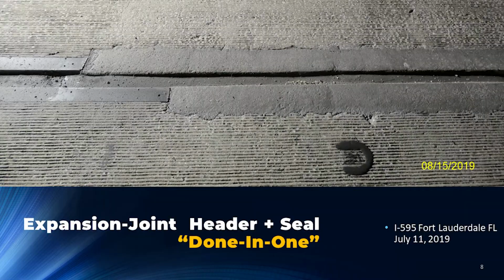So you can see it's pretty corroded, and we were able to reverse that on contact of the rebar without sandblasting. The other part of Phoscrete's ITD program is called the done-in-one, which means you can pour the header with MPC, then as soon as 30 minutes after the final pour, you can remove the foam board, prep and place the joint seal, whether it be a pourable silicone seal, used with backer rod, or using an epoxy or self-leveling foam like M-Seal or any of those other compressed foams.